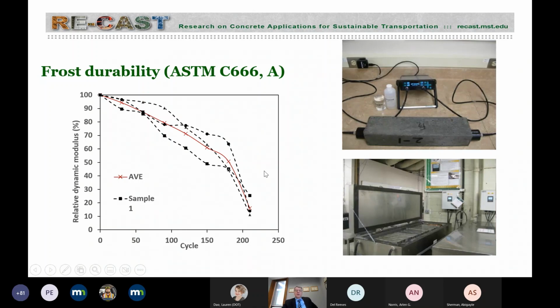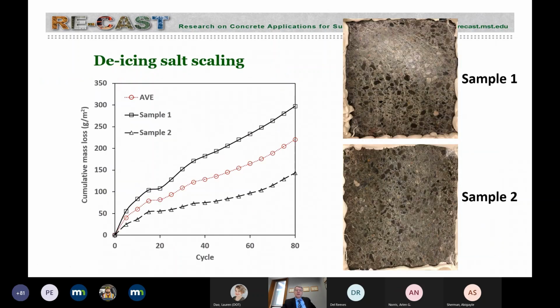In terms of de-icing salt scaling, we did the ASTM C672 test, where we take some samples and pond them with sodium chloride solution for 50 days. We did the test for 80 days because we were impressed how resilient these samples were. And you could see that the average of 2 samples, there's quite a bit of spread, but the average of 2 samples, the cumulative mass loss was still very low.